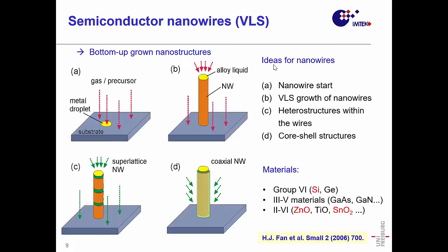and so on. Okay, let me give you an idea how we are able to grow nanowires. The standard approach in literature is called vapor, liquid, solid growth. To give you an idea how that is done, what you do is you prepare either an ultra-thin gold film or a kind of gold dots on a surface. You put that then in your CVD system, and then you supply gases at high temperature. And what happens then is that the gold droplet gets liquid, it's fed by the gas, you have an alloy, and then supersaturation, and if you have a supersaturation, then the wire grows.